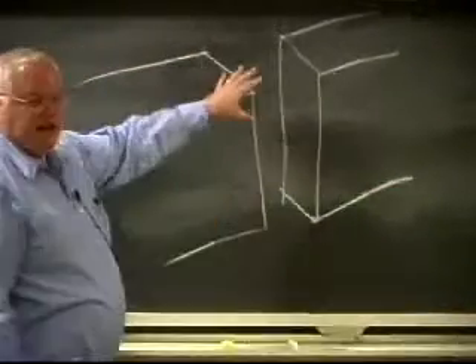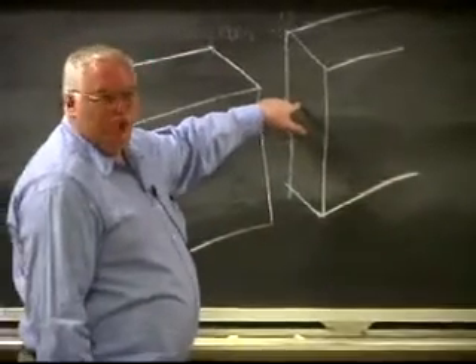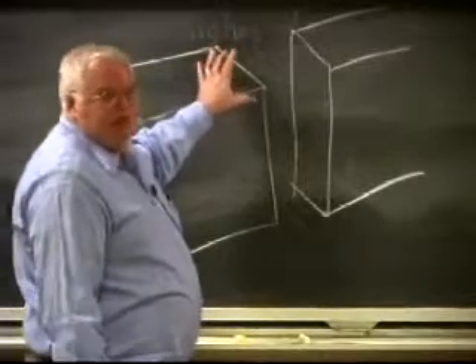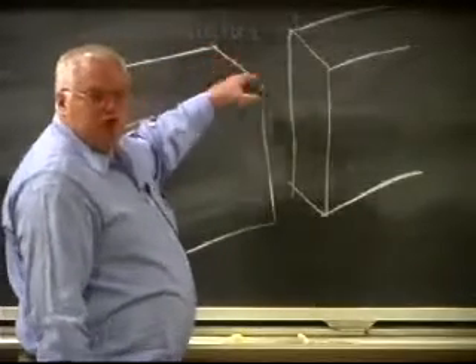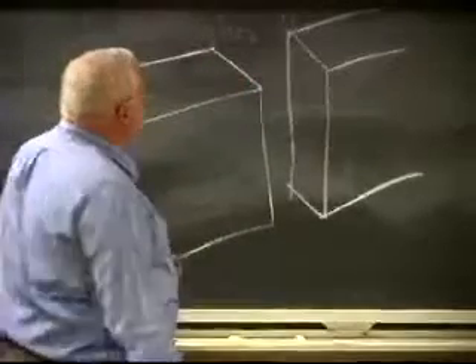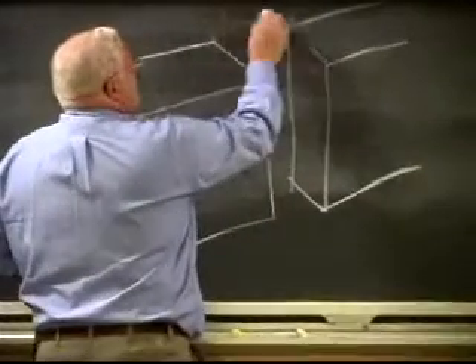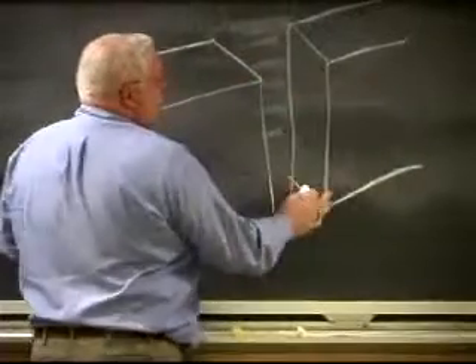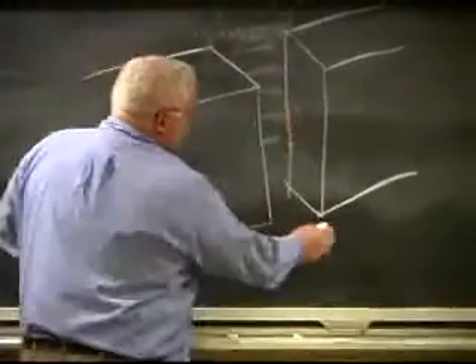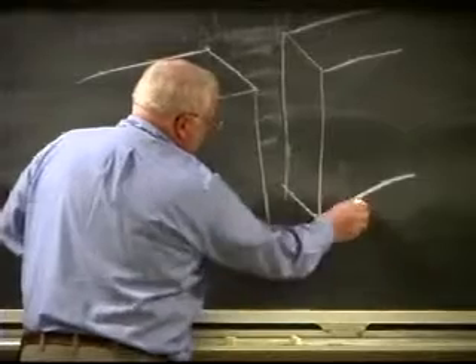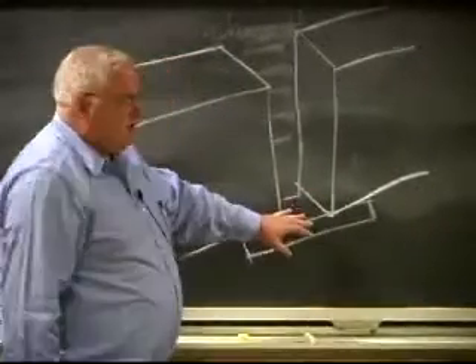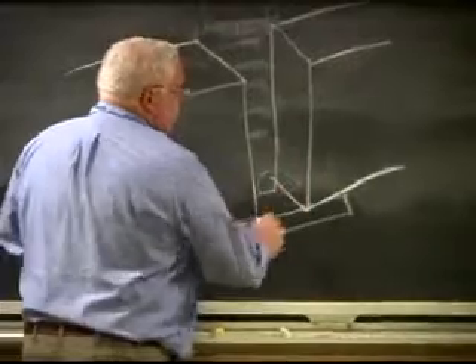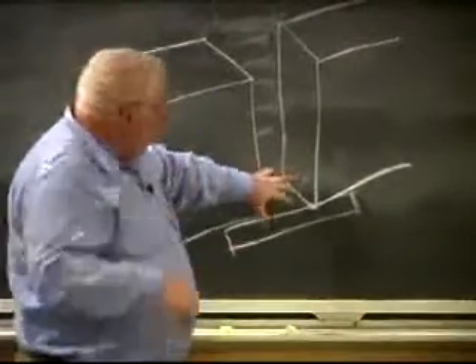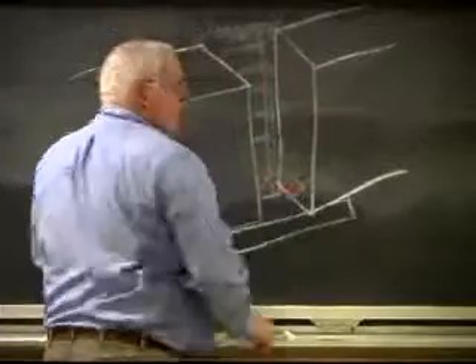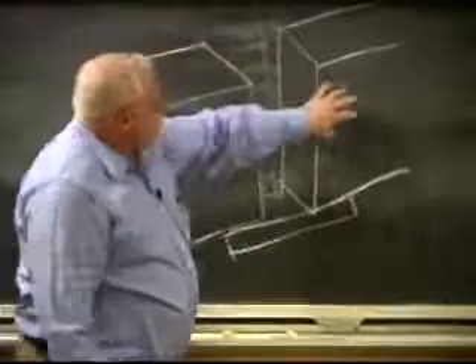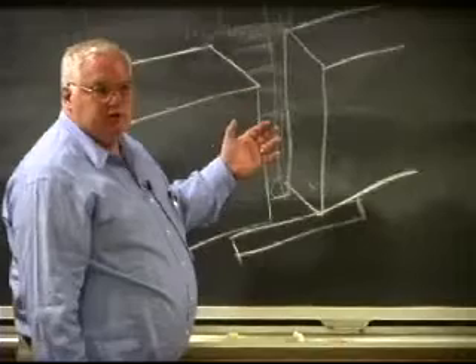If I have two plates and I have a gap, and that gap could be an inch, inch and a half wide. Sometimes we electroslag weld 1-inch plates, but we prefer to do 2 or 3 or 4-inch plates. You put a copper dam on the back side and then another one on the front side. You put a steel or a titanium plate, in this case, on the bottom to create a base. You pour a little bit of this submerged arc type flux, this granular sand, in here. You feed a wire down in here, and I now have a casting cavity with titanium plates on 2 sides and water-cooled copper on the other 2 sides.